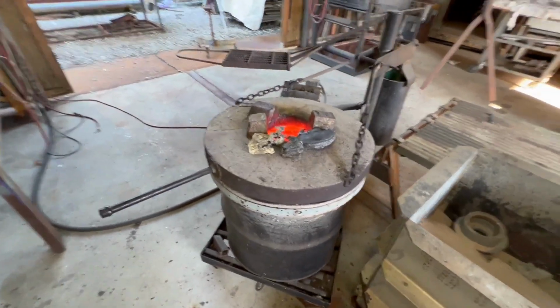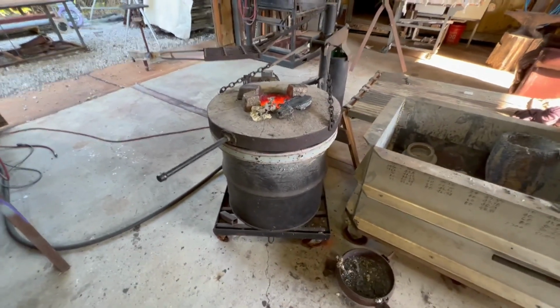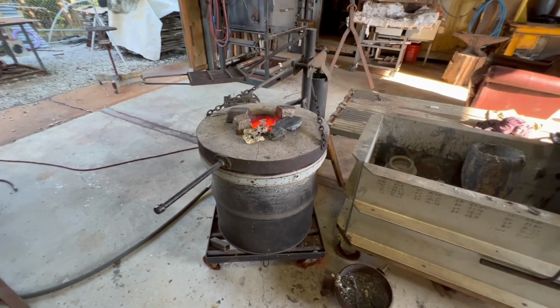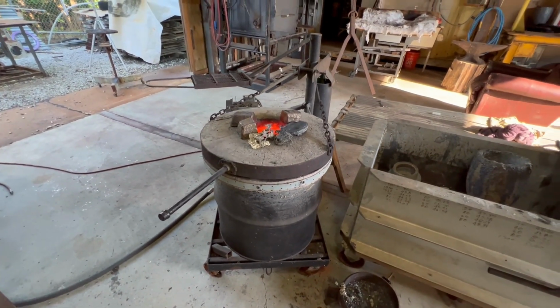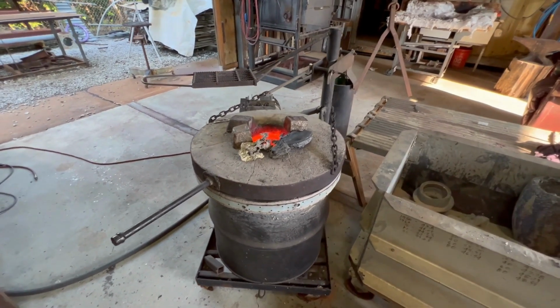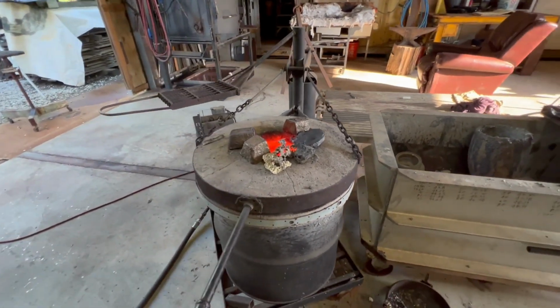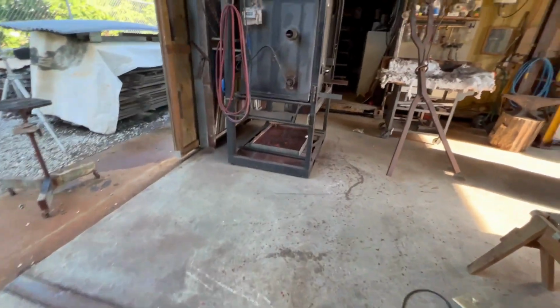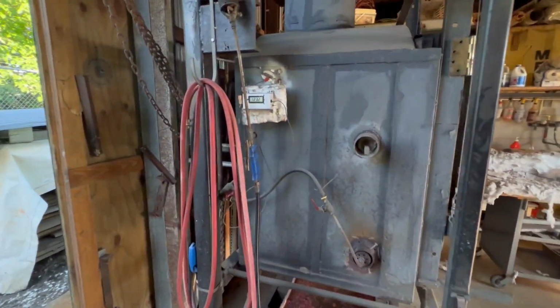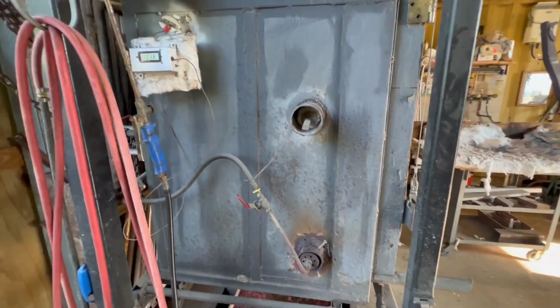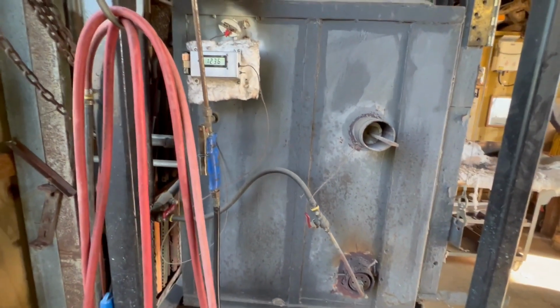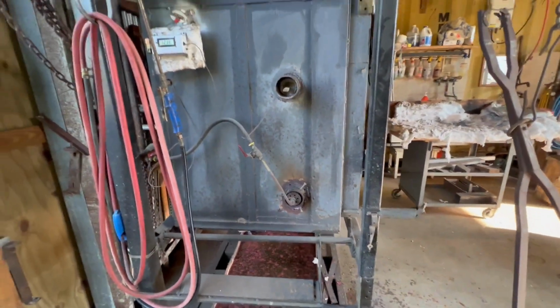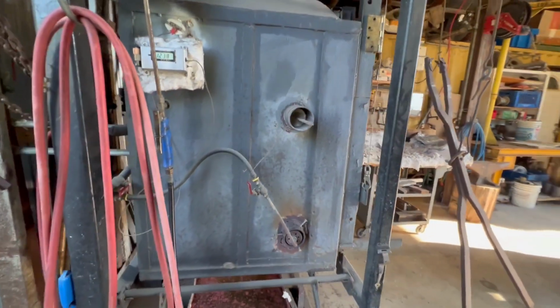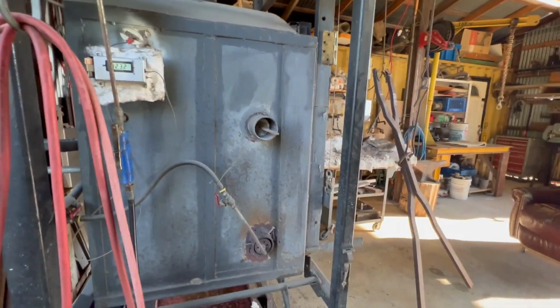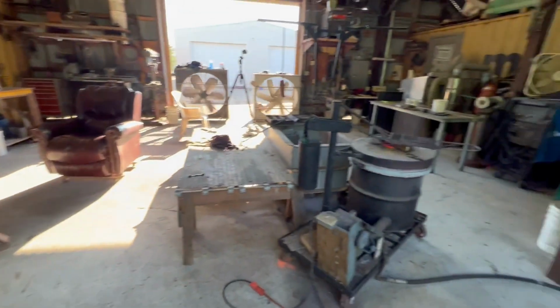So that's why I like to put lots of little scrap pieces in the bottom first, and then once they start melting and you get a little liquid in the bottom, the bigger chunks melt a little quicker. It's kind of exponential. And we have the kiln on. We're soaking the molds. We're at 1200 degrees right now. These heat up real fast, so at the last minute I can turn up the flame and get them up to around 1800 degrees. We want them as hot as we can handle them to make sure the bronze flows freely without freezing.